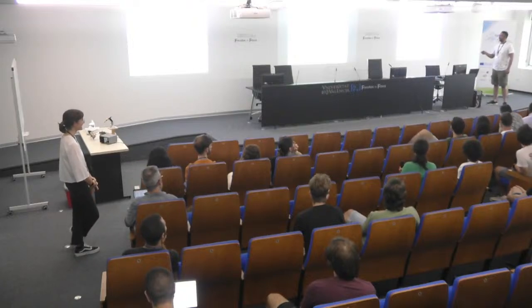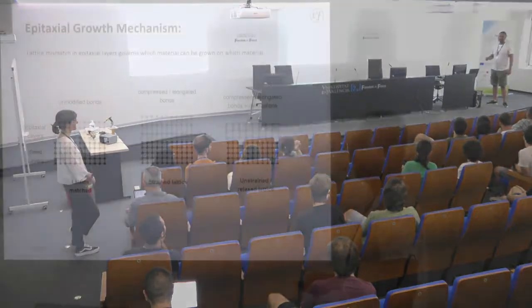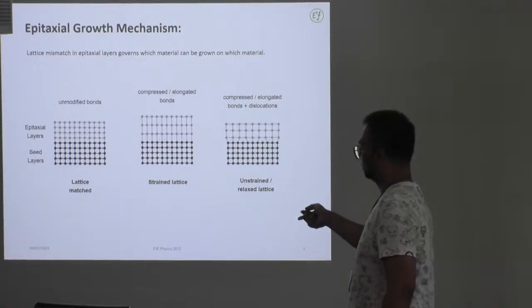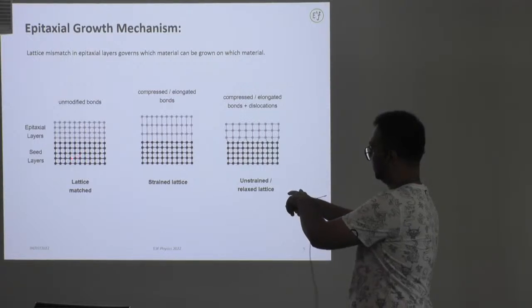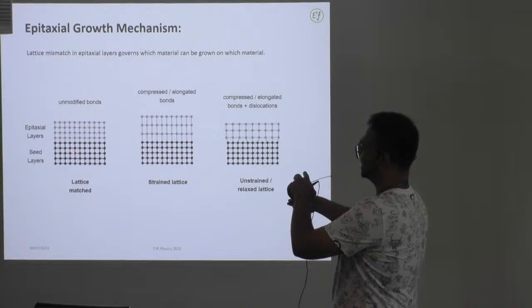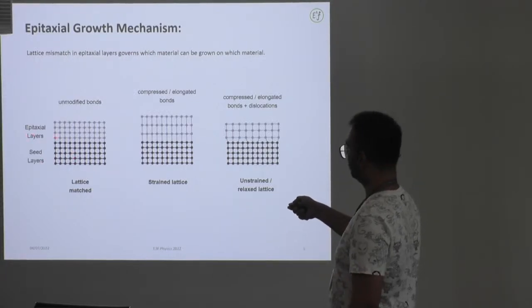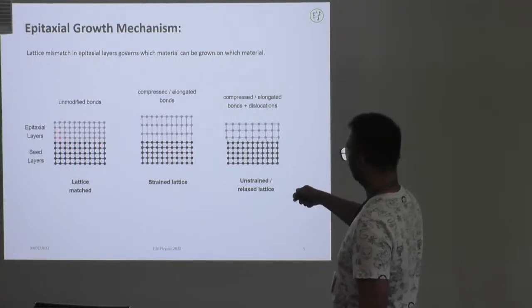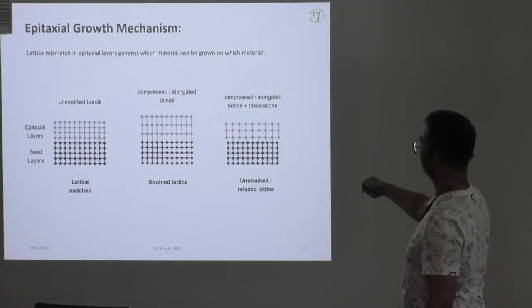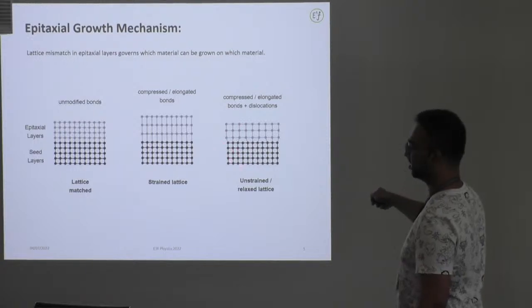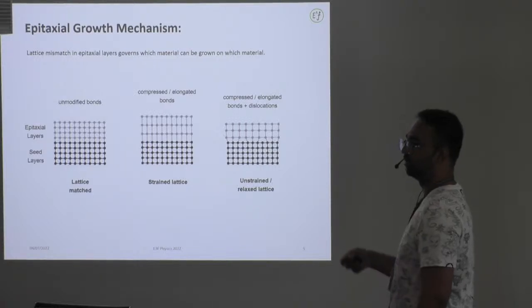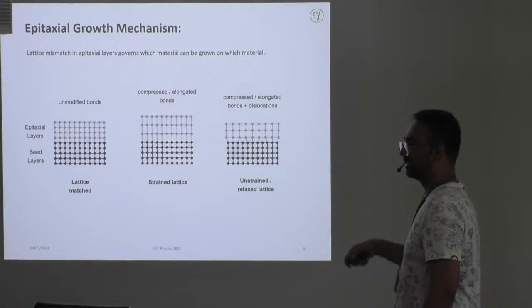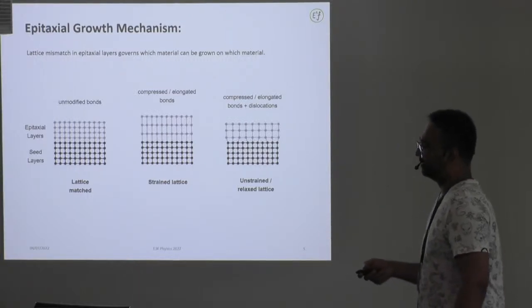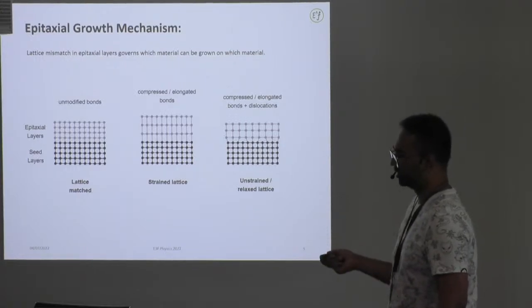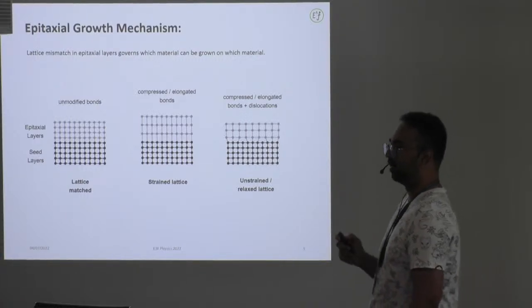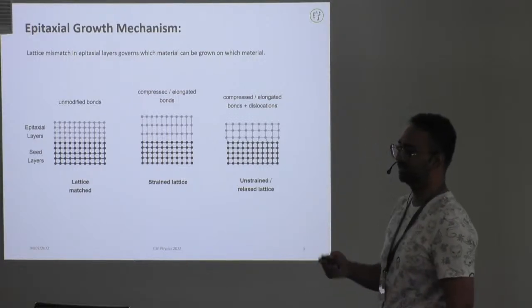So, as I mentioned, there is this lattice structure. It has to match where it is going to grow. If, let's say, these squares, as you see here, have different dimensions for tungsten diselenide and the silicon substrate, it will not grow there. It will prefer to grow on itself because it will match very easily. But if you have, let's say, this silicon oxide is this and tungsten diselenide is this, you see there are some dislocations, and there is also some strain and compression. So it will not prefer to grow there. It will just prefer to grow on itself. That is something you have to deal with, and it goes much more in detail, because for that you should not use pulsed laser deposition or magnetron sputtering, but you should go for MBE, molecular beam epitaxy. But that is a separate presentation, I would say. Okay, thank you.